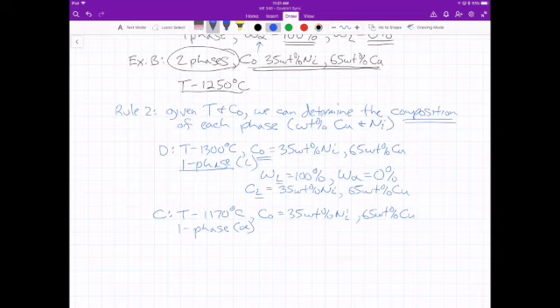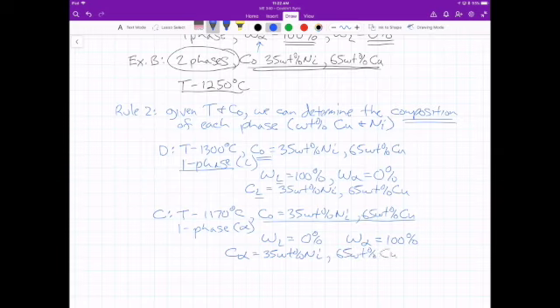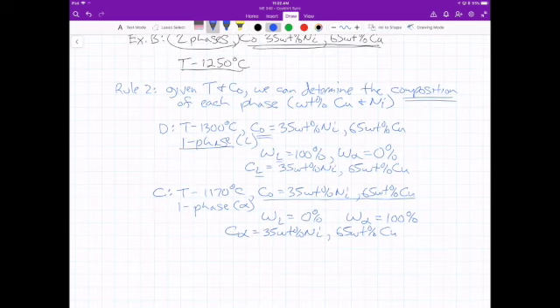So if that's the case, the weight fraction of liquid, weight fraction of solid: if we're completely in the solid phase, there's one phase, we have to have 100% of that phase, which means we have 0% of the other phase. And again, the concentration, since there's one phase, is the same, but this time the concentration is in the alpha phase, and that would be 35 weight percent nickel, 65 weight percent copper. So let's look at B. Point B gets a little more complicated, but the math is actually very simple.